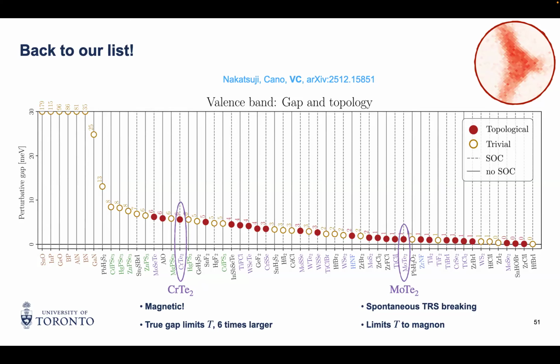And in that case, what will limit the stability of your system is the true gap that I've extracted here, so the single particle gap between the two moiré bands. And it turns out that this one in our calculation has a gap that's 6 times larger. So again, if you really want to simulate topological phases, or at least topological bands, this is the one material I would advise to use, at least from this small scale calculation.